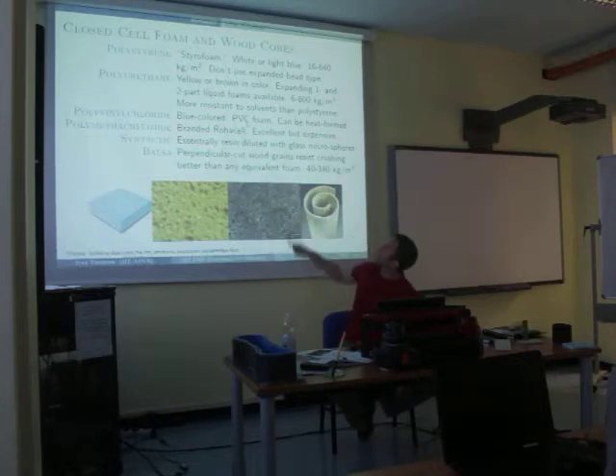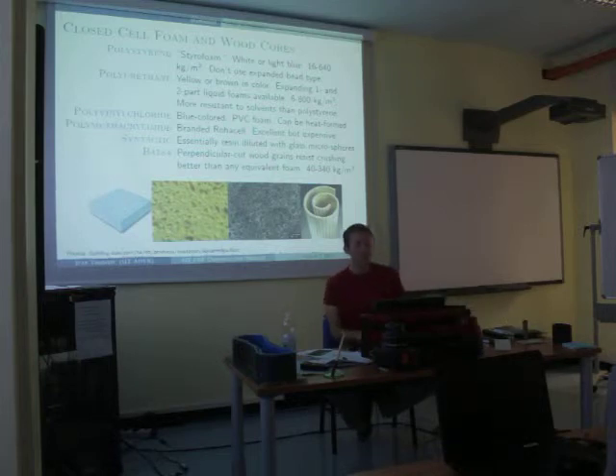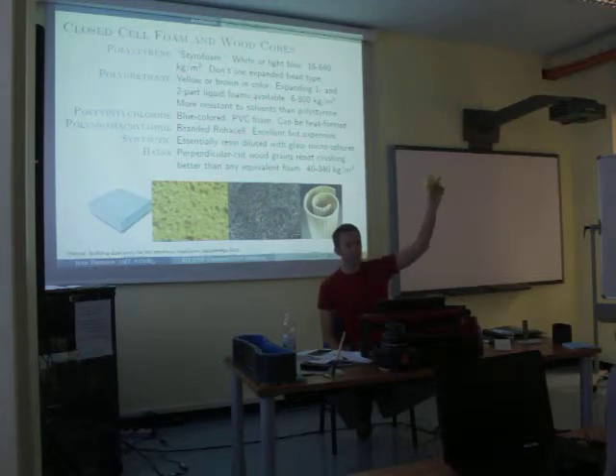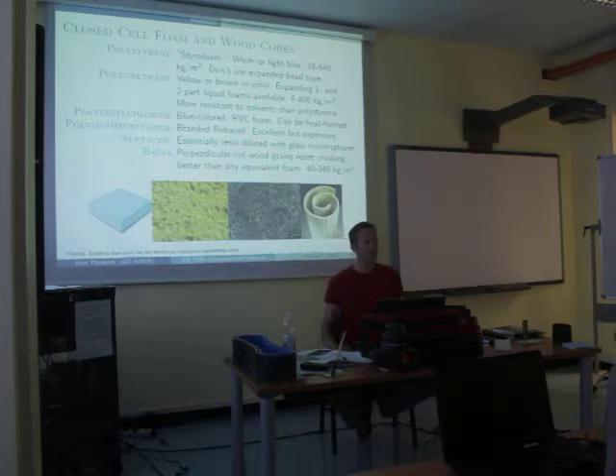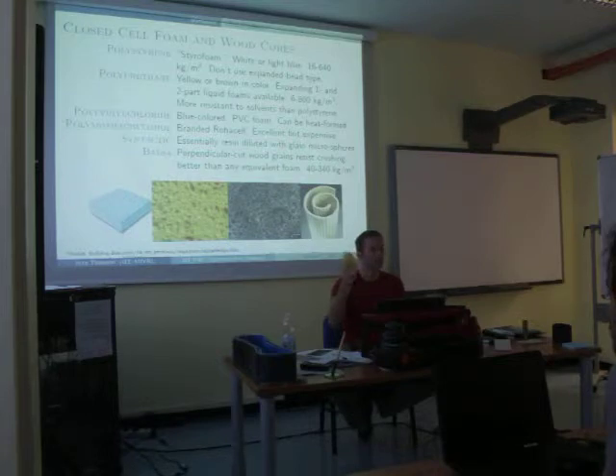So the yellow polyurethane foam is brown in color. You can get pre-expanded 1 or 2 part liquid foams. This was a 2-part liquid polyurethane foam. Some of you may be familiar with polyurethane foam that comes in a can, and you can spray it. That requires air to cure. I actually tried using that to make some of these pieces, and even after 24 hours in a mold, they hadn't cured because they don't have any air in the mold, and then I had a big mess to clean up. So then I went and bought some 2-part polyurethane foam, which I mixed, and you can pour it into a closed cavity, and it forms a nice foam structure which you can make in sort of any shape if it's a liquid foam. You do need to make a mold, but it was pretty useful.